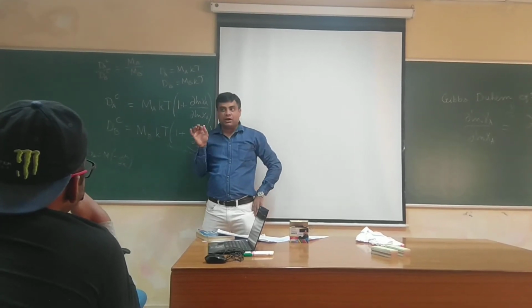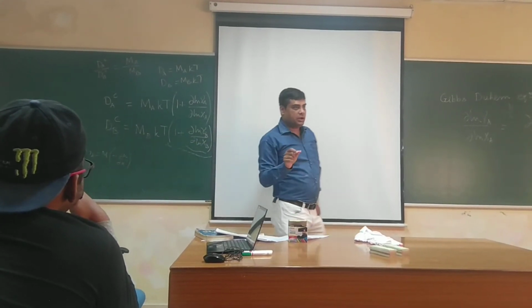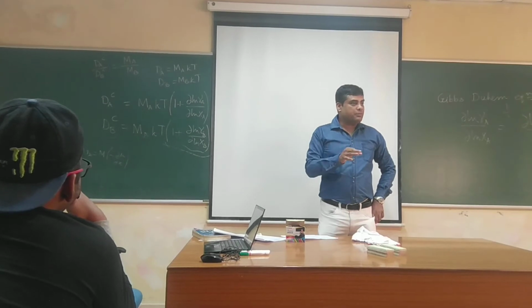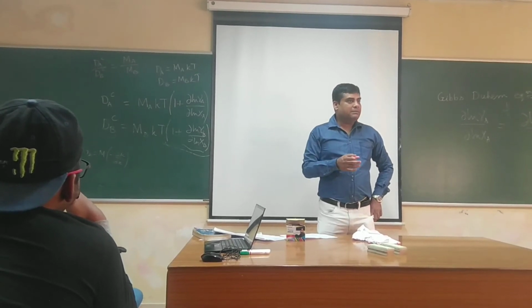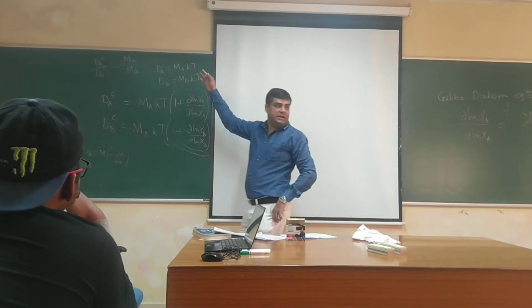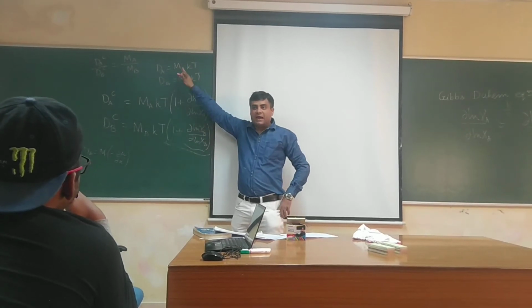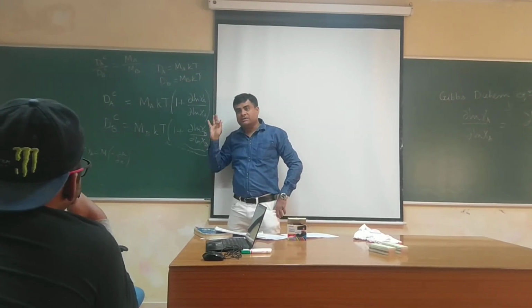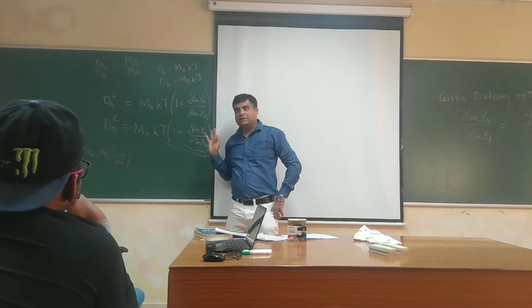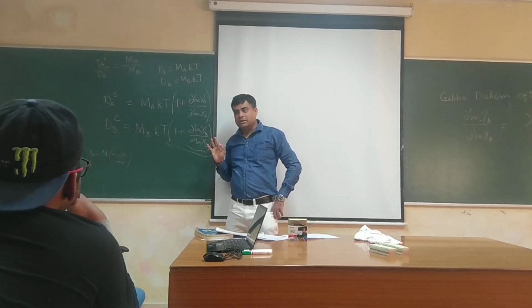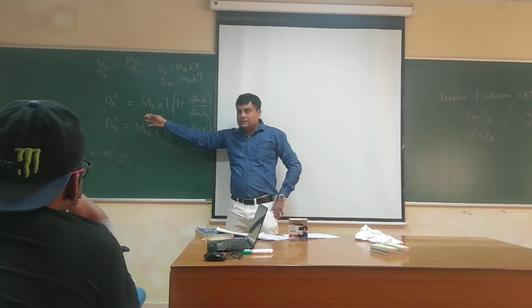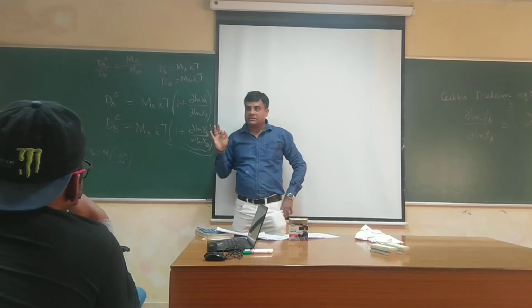In the homogeneous alloy, what is the composition of that alloy? Mobility. So if you change the composition of the alloy, you will find different mobility. So mobility values are function of composition. Thermodynamic factor values are function of composition. So as a result, the DB, DA are also function of composition.